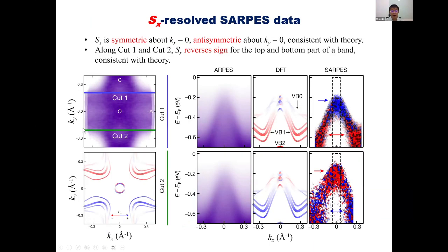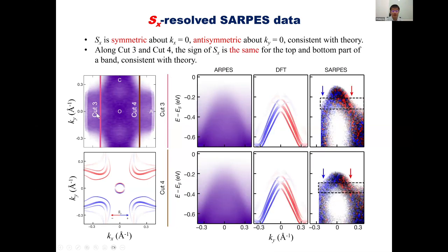First of all, we cut along these two lines and do a spin-ARPES measurement. The blue and red here correspond to two different types of spin. When we cut along cut 1, the top is blue and the bottom is red. When we cut along cut 2, the top becomes red and the bottom becomes blue. So it is exactly antisymmetric with respect to the ky equals 0 line, which is also consistent with our calculations. Next we do cut 3 and cut 4.